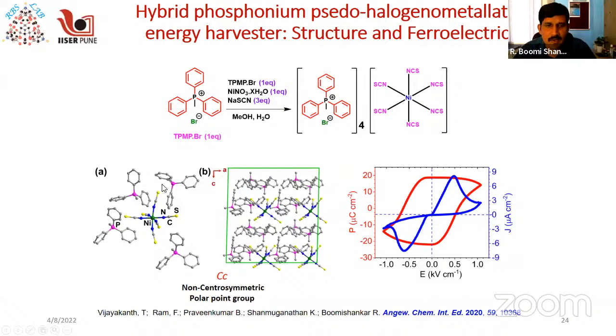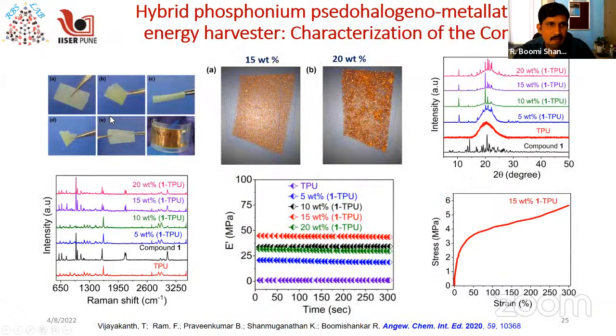So this molecule again crystallizes in a non-centrosymmetric space group. It shows a ferroelectric polarization and JE curves typical for a ferroelectric material. And then we made flexible composites of that. We can also visualize the location of the ferroelectric particles in the polymer matrix using 3D X-ray tomography techniques.